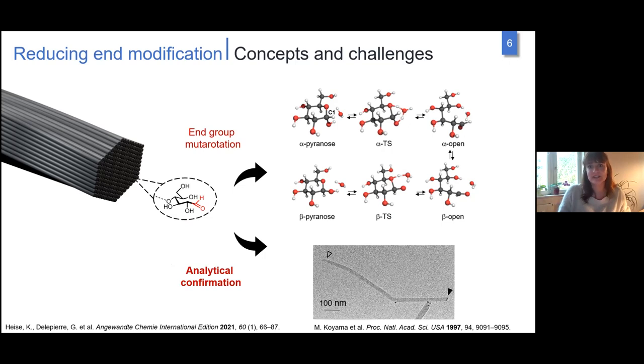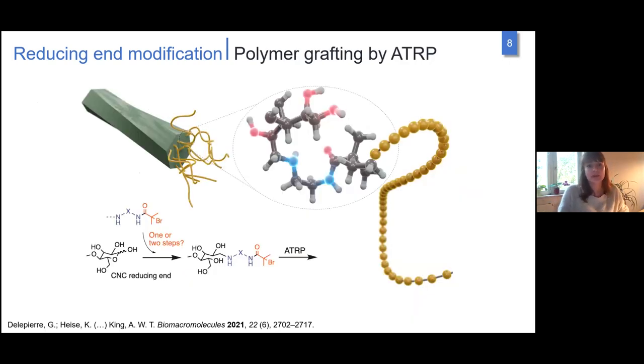It's an acid-base catalyzed reaction which can be catalyzed by water. We just need one water molecule to open the ring and shift the equilibrium towards the open chain aldehyde. Another challenge is analytical confirmation because the amount of newly introduced functionalities at the reducing end is very low.